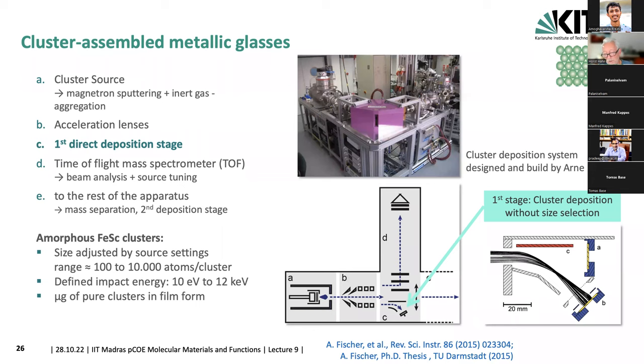So we deposited amorphous clusters of iron 80, scandium 20, which forms an amorphous particle easily, which then was in a cluster state, so very small clusters, and we deposited them with different impact energies. So we smashed them hard on the substrate so they can spread out and rapidly quench again, or we do soft landing and we hoped to build interfaces in between.